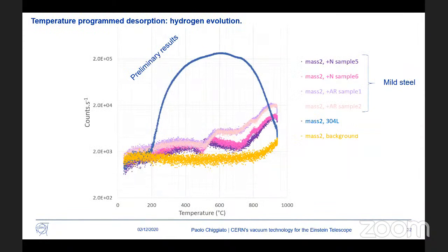What we have shown is quite striking, I would say: there is an important difference between the austenitic stainless steel and the mild steel in terms of gas release. In particular for hydrogen, you see that the blue curve on the top is the desorption of hydrogen as a function of temperature for the 304, while all the curves down there, except the orange one, which is the background of the system, are those for the mild steel. This reflects the fact that the total content of hydrogen for the mild steel is roughly two orders of magnitude lower than the one for austenitic steel.